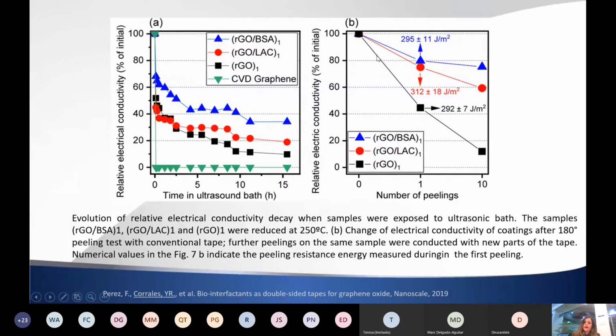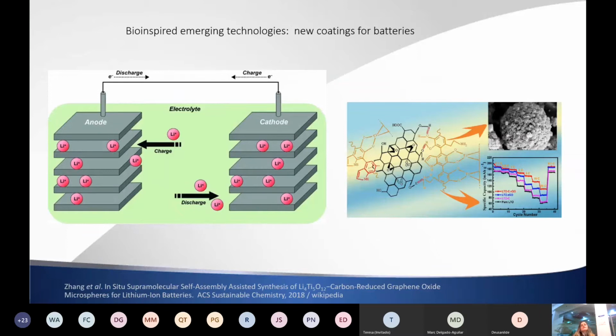And also we saw that the conductivity, also that they were really stable. So we went another step further, and as we know nowadays, we have the lithium titanium oxide anode and cathode materials. And now everybody is working on producing nanoparticles and trying to improve this material. But what happened with the lithium-based materials is they are not so well conductive. So whenever you build an anode or a cathode or a battery, you need to add carbon black, or graphene, and now everybody's using graphene oxide.